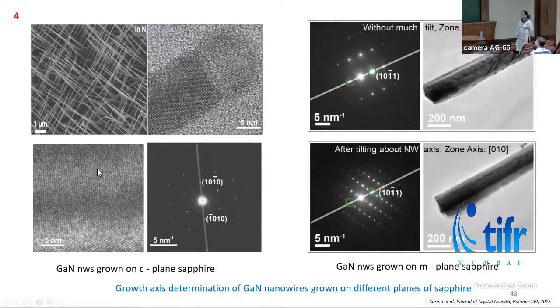We check the composition of the tip, we check the composition of the wires, and another important thing is checking the growth direction of the wire. By indexing the diffraction pattern, we can confirm that the wires grown on C-plane sapphire grew in the 10̅1̅0 direction, and these are the wires grown on M-plane sapphire, which, after analyzing the diffraction patterns, we could find were grown in the 10̅1̅1 direction.